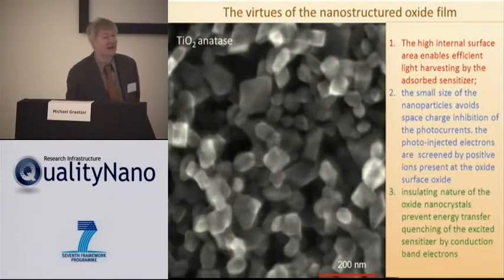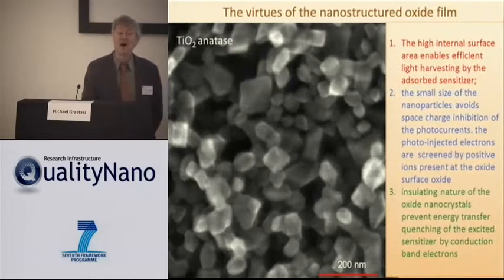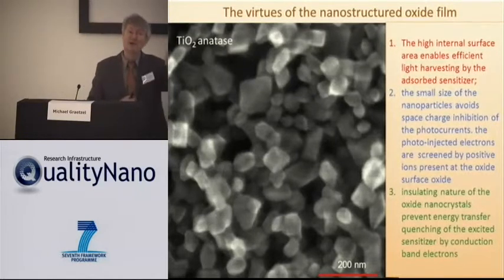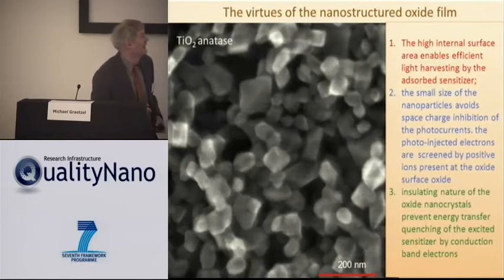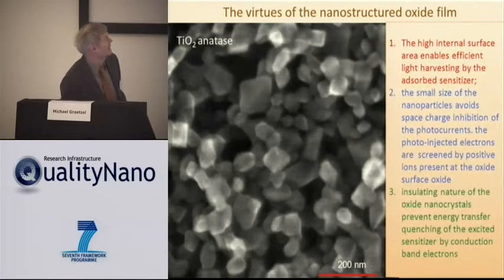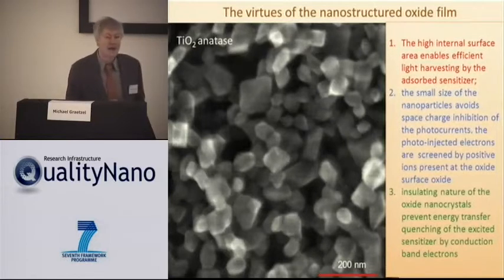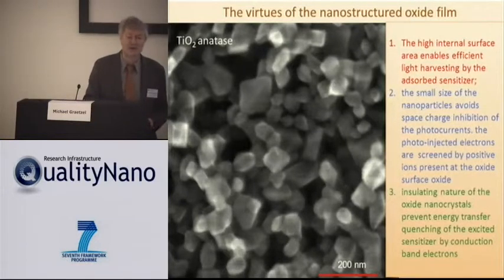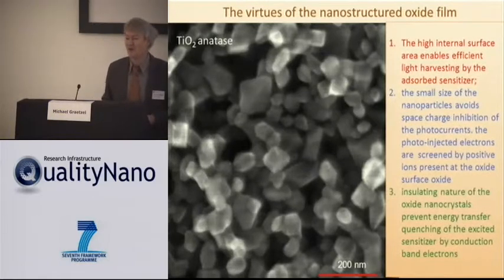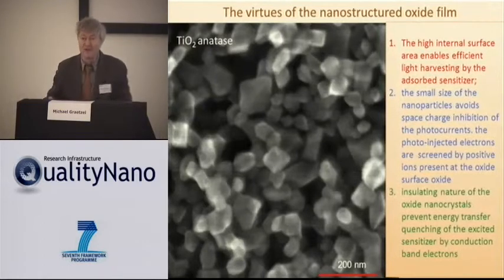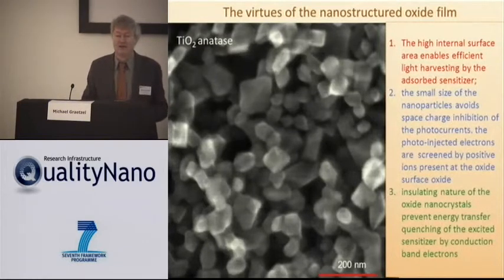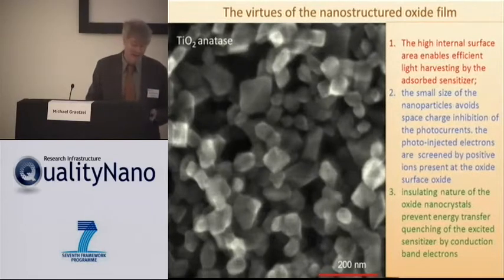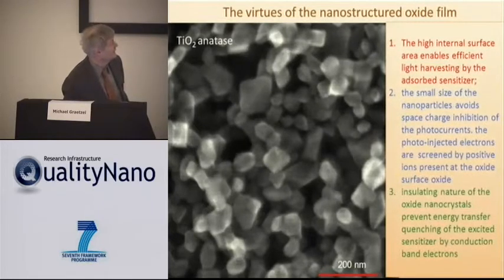And now you inject an electron in the conduction band, it makes a charge. And so if you want to put another electron in, you have a repulsion. It's called the Coulomb blockade or space charge limitation. And so this doesn't happen on the nanoscale because we can screen the injected electron by positive charges that are on the surface, from the electrolyte or from the ions that are anyway on the surface of the titanium. So this is the key.